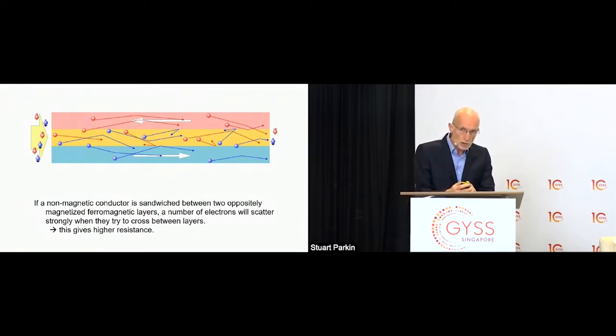So now when we introduce current from a battery, the red layer will support electrons which have their polarization up, and the blue layer will support electrons which have their polarization in the opposite direction. And because this is a metallic system, electrons from the red layer will cross this copper layer and then be scattered in the blue layer, and vice versa. So innately, this system, where the moments of the two magnetic layers are antiparallel, will have a high resistance. The electrons will always be scattered strongly somewhere in the layered system.